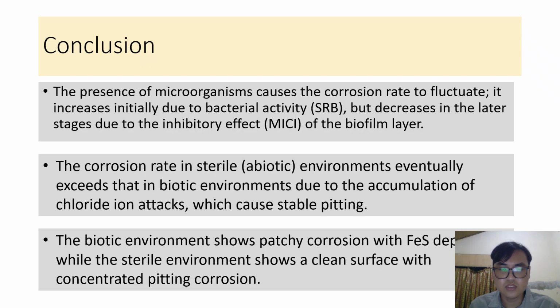To conclude, the presence of microorganisms causes the corrosion rate to fluctuate. It is high initially due to bacterial activity, but decreased later due to the inhibitory effect of the mature biofilm. The sterile environment eventually becomes more destructive in the long term due to the accumulation of stable pitting corrosion caused by chloride ions. This is the crossover phenomenon. Morphologically, biotic environments result in uneven, patchy corrosion with iron sulfide deposits, while sterile environments result in deep localized pitting.